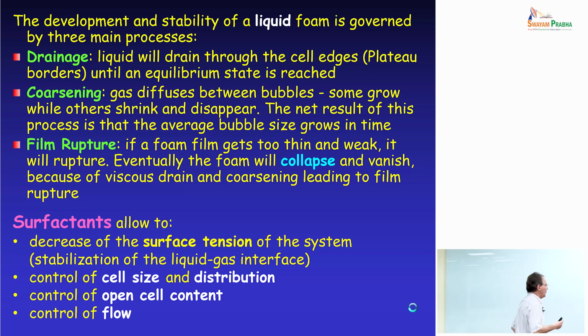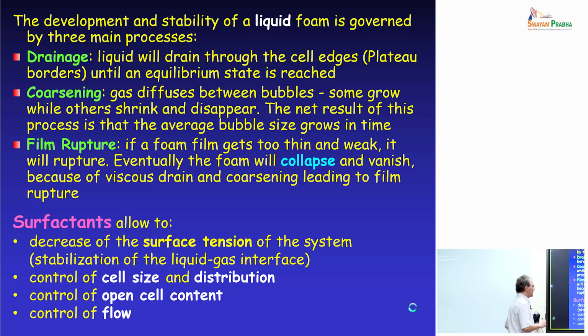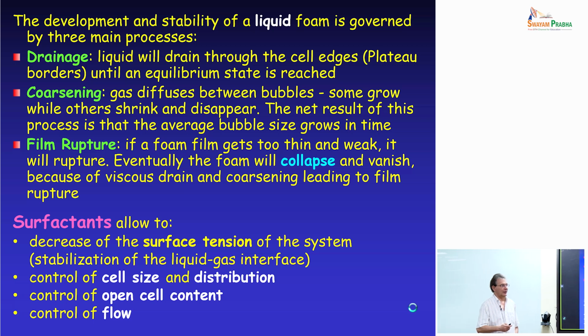So people can use surfactants to decrease the surface tension of the system, so you stabilize the liquid-gas interface. You can use surfactants to control the cell size distribution, control the open and closed cell content, and also control the flow of the drainage of the liquid.